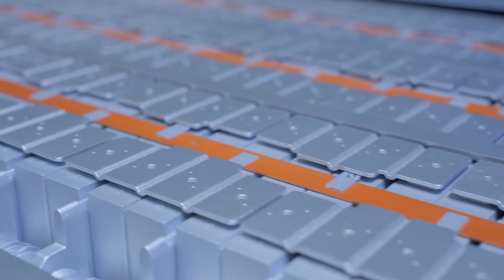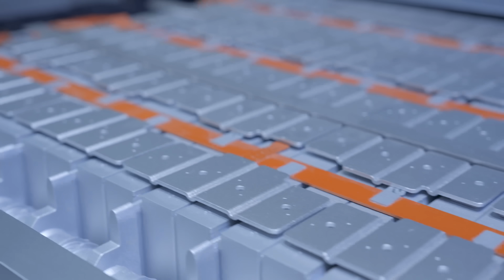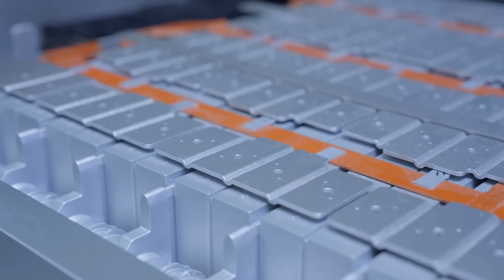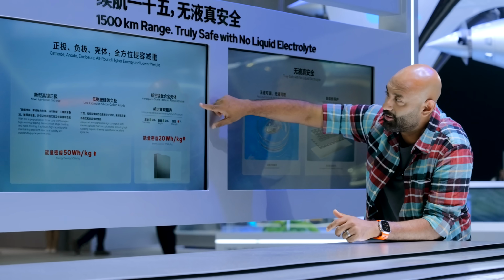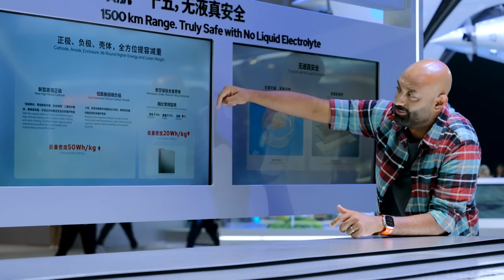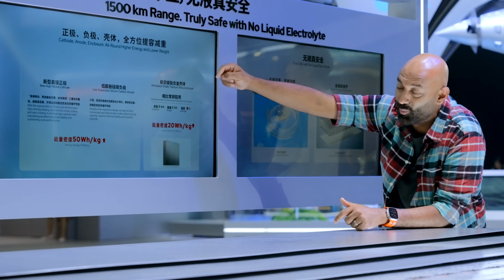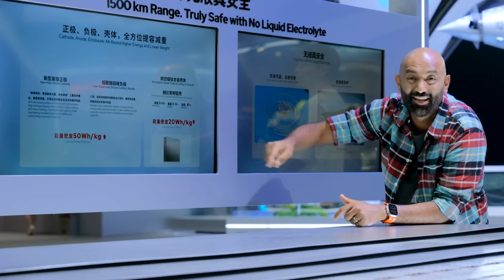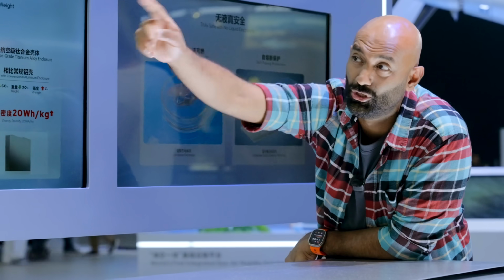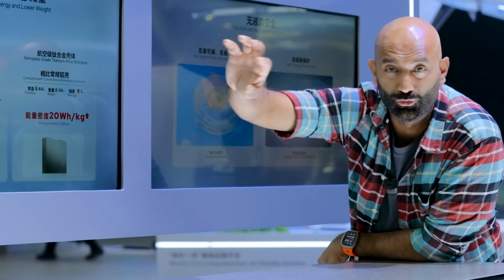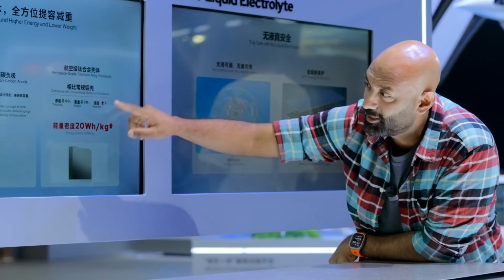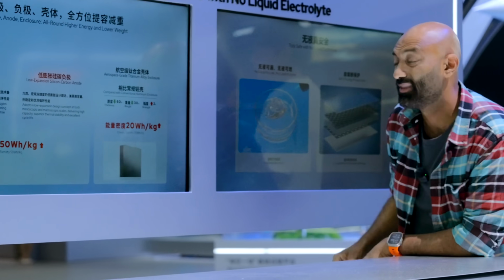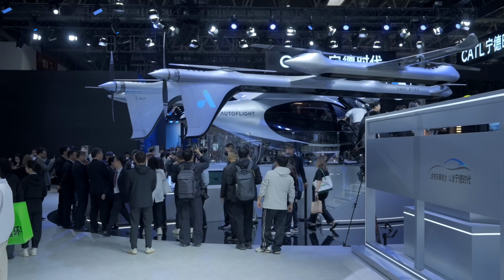Now, titanium is really, really nice. It's incredibly strong and lightweight, but it's expensive. But here, by comparing it to a traditional aluminum enclosure, they're able to drop the thickness 60%, the weight 30%, and the strength is twice as strong. So the 280 on the Qilin traditional pack, plus 20, plus 50, gets us to 350. Pretty amazing.